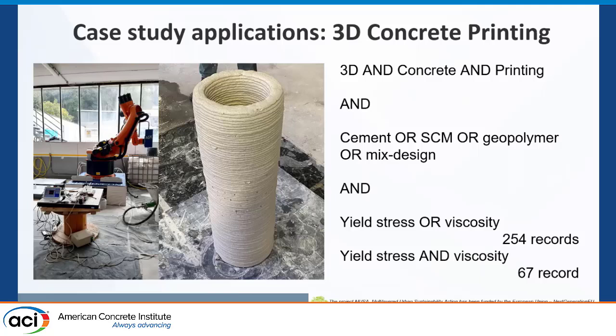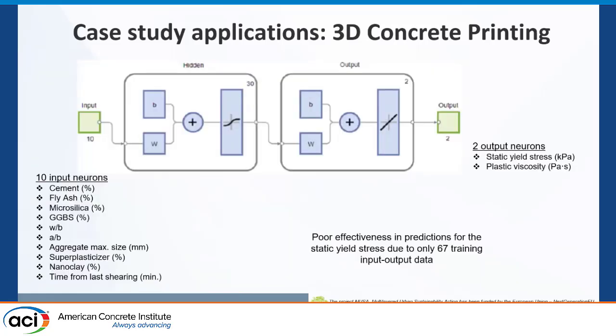If you ask yield stress and viscosity, which means that the study measured both properties, the number of records is greatly reduced. It's true that viscosity is not so important in the sense of the printability. The yield stress governs more, but you can ask for it as well. So we started building up our neural network. We started with 10 input neurons dealing with the data on the mix design, and we tried with 2 output neurons, the yield stress and the viscosity. Very poor prediction because we had very low data.